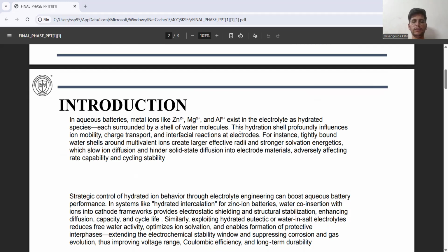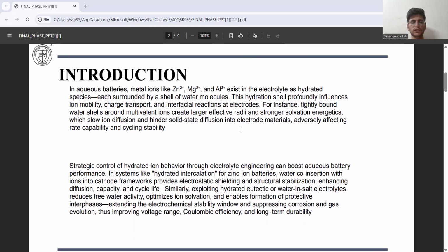Strategic control of hydrated ion behavior through electrolyte engineering can boost aqueous battery performance. In systems like hydrated intercalation for zinc-ion batteries, water co-insertion with ions into cathode frameworks provides electrostatic shielding and structural stabilization, enhancing diffusion capacity and cycle life. Similarly, exploiting hydrated eutectic or water-in-salt electrolytes reduces free water activity, optimizes ion solvation, and enables formation of protective interfaces, extending the electrochemical stability window and suppressing corrosion and gas evolution, thus improving voltage range, Coulombic efficiency, and long-term durability.